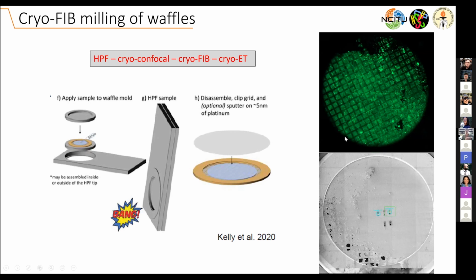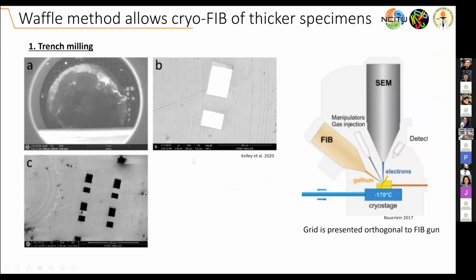And then you can add a cryocorrelation step where we screen the sample by fluorescence microscopy. So here, those are plant cells that were processed through the waffle method. And here we're imaging the autofluorescence of plant cells. So basically the plant cells are everywhere, so we don't really care about FIB milling at specific points. And then the FIB milling occurs in two steps. So here we're dealing with samples that are much thicker, in the range of 20 microns.